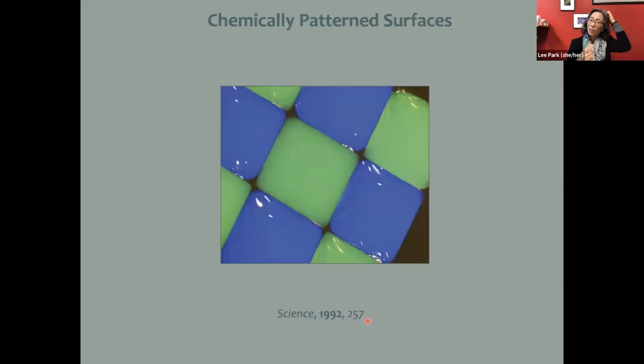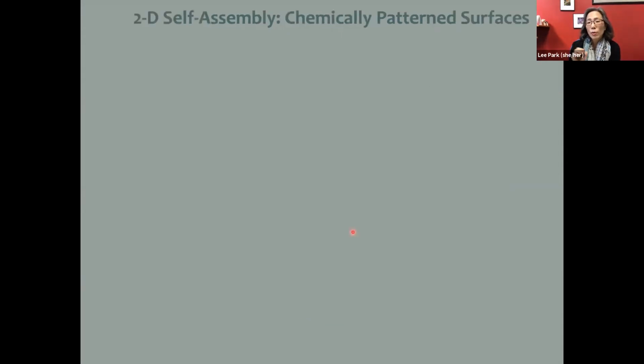Okay, so this is a very early image from one of the groups that originally was doing this kind of work. And in this case, they drew lines of the hydrophobic material along their surface, and then they put down water. So this is water with some fluorescent dye in it to make the picture a little more interesting. And you can see that you can control where the water wets the surface. And so in this case, you're able to make these square water droplets. And so that makes for a really fascinating image. But of course, square water droplets is not really the goal. So what can we do with this? So what we might want to try to do is think about how we can pattern a surface. So we're trying to chemically pattern a surface.